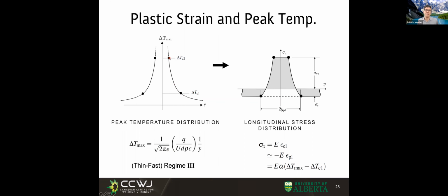And when we reach the delta TC2, that is plasticity during cooling, we know we're going to end up with a final residual stress that is yield stress. So our final state of stress is going to look like this one here. This amount is the residual stresses in tension due to the plasticity. This is where it had plasticity both ways. This is yield stress. This part is when it sees plasticity during heating, but not during cooling. And these wings are in compression to make up for the tension near the weld.